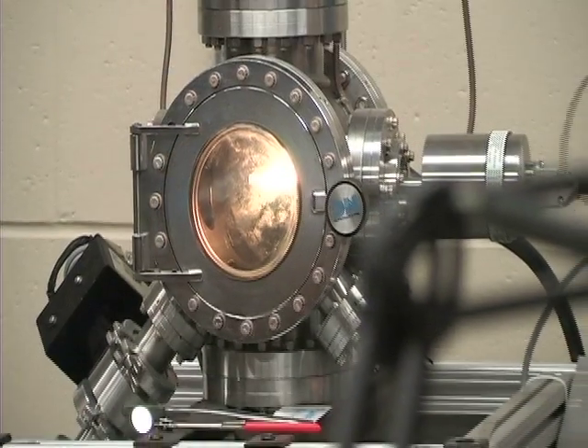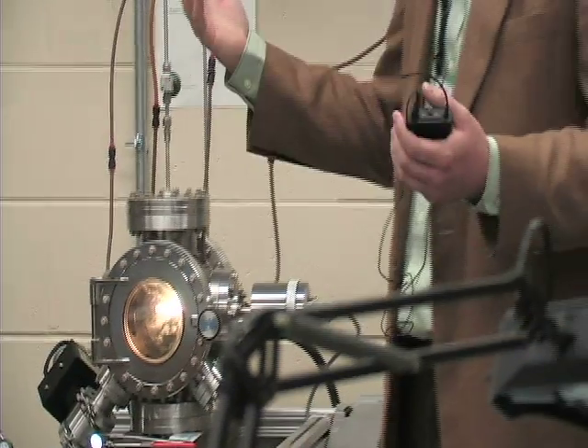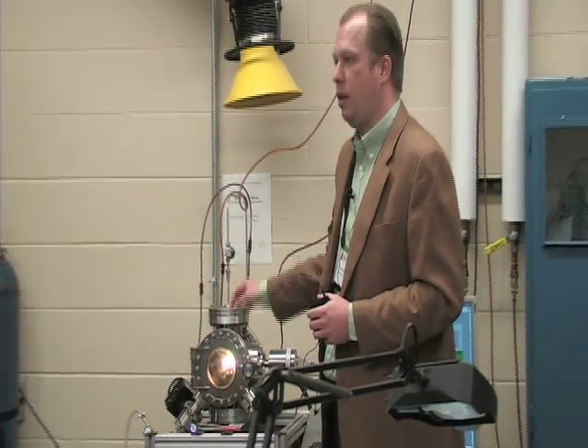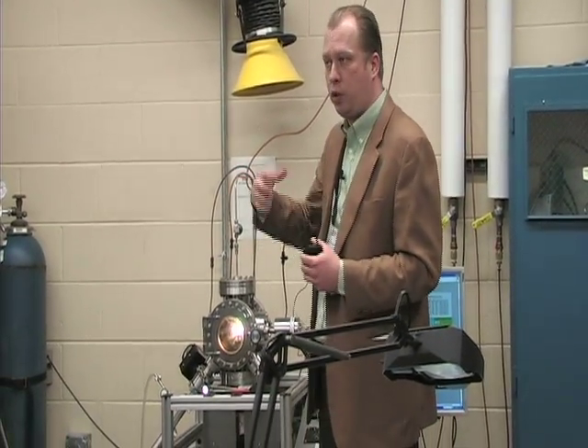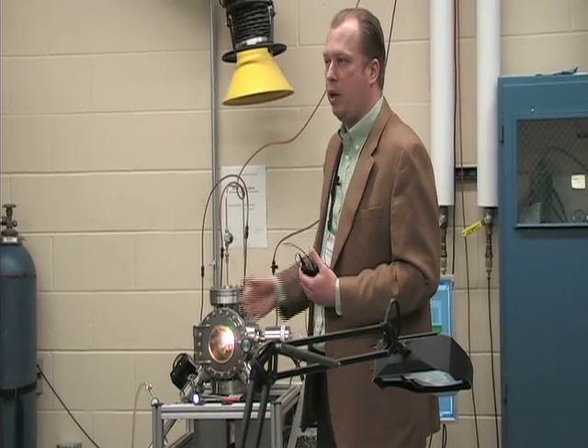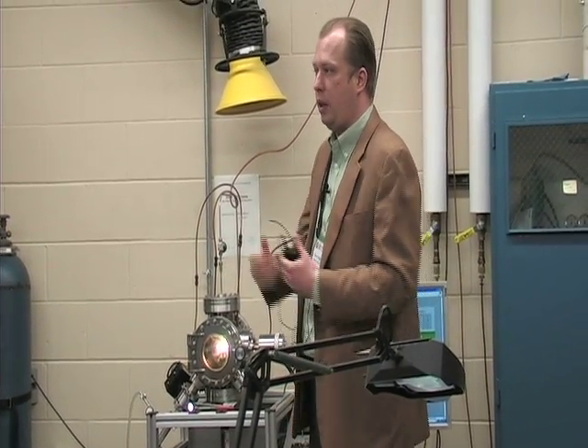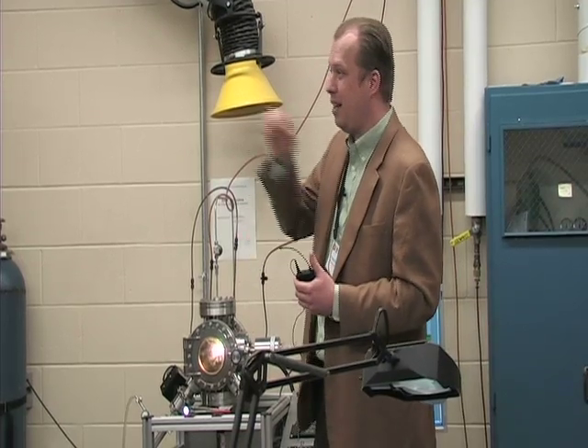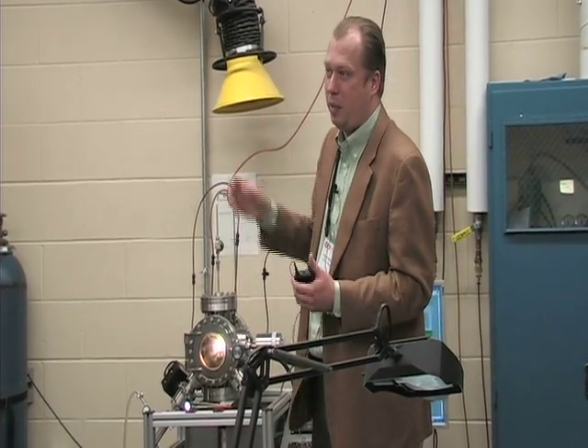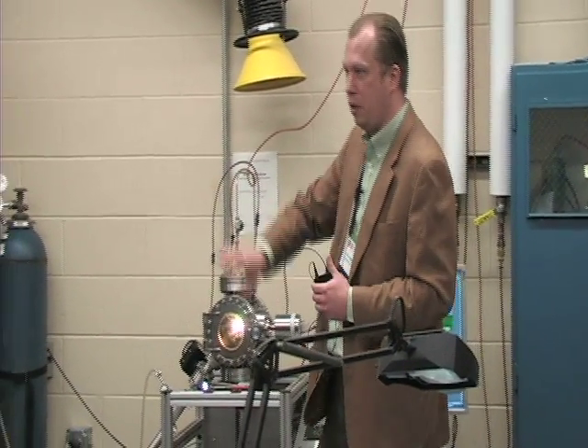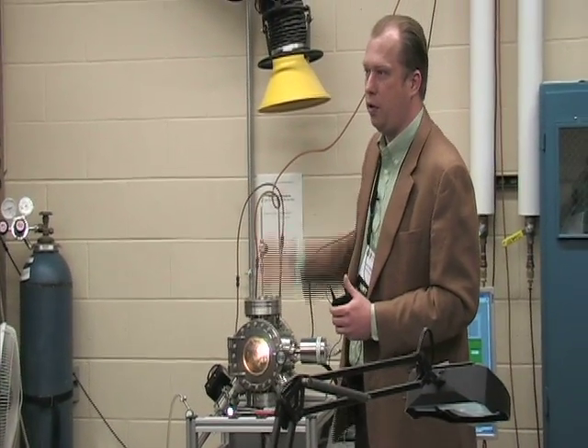Even with something as easily machinable otherwise as aluminum, we can see sometimes significant force reductions when we're micro end milling with the diamond coatings because there's less adhesion. And also a big thing, the chips don't stick in the flutes. I mean, not even just talking the cutting zone, but evacuating material up the flutes of the micro end mill.